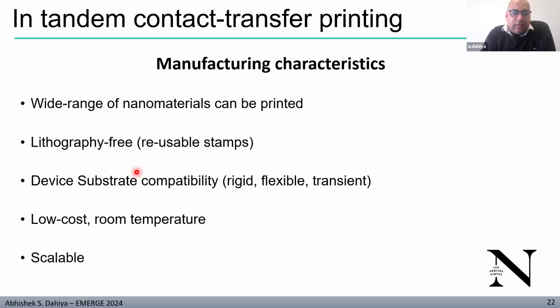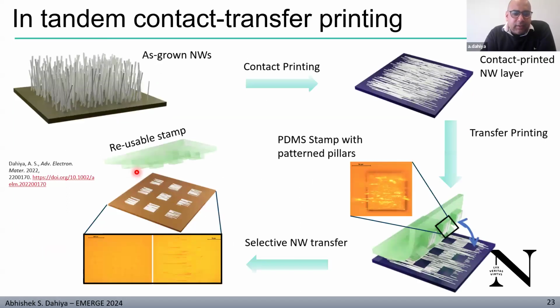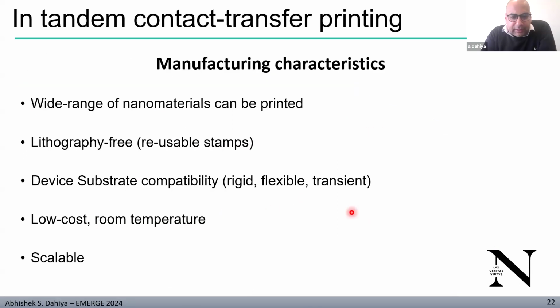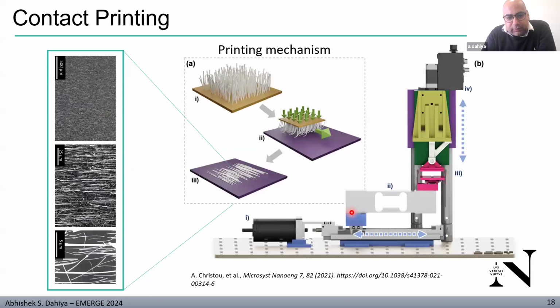Currently, yes, this is a two-step process and it has a very poor yield. For example, if you see the density of wire onto the printed area, the yield is lower. In the beginning, in the contact printing, the density you can transfer is quite high, right? Once you are using this approach, you are only able to print 10 to 20 nanowires in a 100 by 100 micrometer area. So yes, the yield is lower. Currently, we need to work on that aspect.